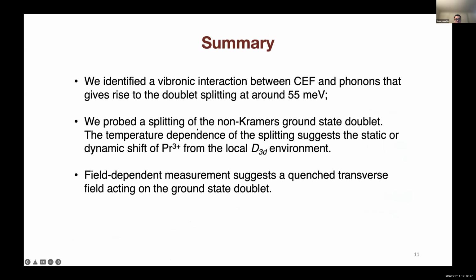So in summary, we present a high resolution temperature and field dependent Raman scattering study of crystal field excitations in praseodymium zirconate. And we see a Fano-like interaction between the crystal field levels and the phonons, and we probe the splitting of the non-Kramers ground state doublet, indicating the static or dynamic shift of the praseodymium 3+ from the local environment. And the field-dependent measurements suggest a transverse field acting on the ground state doublet. And with that, I'd like to thank you for your attention, and I'm happy to answer any questions you may have. Thank you very much.